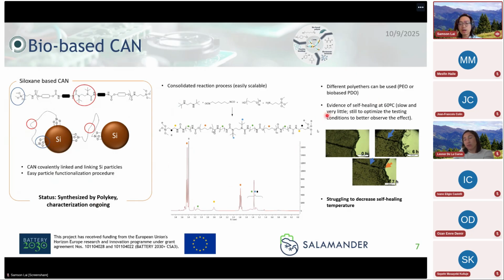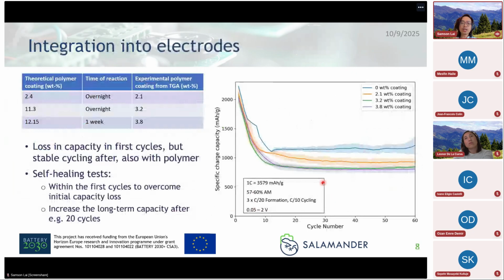So we had a coating, we were testing different loadings of the coating of the silicon particles with this polymer. We're able to get about 2, 3%, 4%. And we're able to actually see some nice, decent electrochemistry. So again, kind of using this reverse approach to what we have. So we still have to see whether we can actually, let's say, heal the damage and do the self-healing, but at least we've finally made some progress after a long struggle in the beginning.